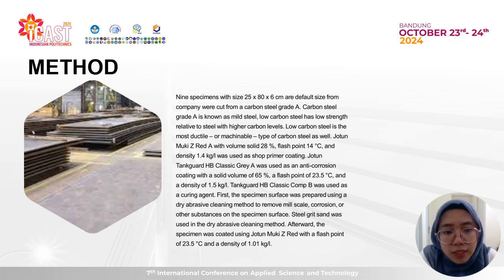The low carbon steel is the most ductile or machinable type of carbon steel as well. Jotun Muki Z Red A with a volume solid of 28% and a flash point of 14 Celsius was used as subprimer coating, and Jotun Tankguard HB Classic Grey A was used as an anti-corrosion coating with a solid volume of 65%, and Tankguard HB Classic component B was used as a curing agent.